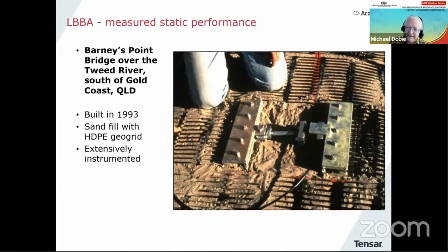And also because, again, it was early use of this technology in Australia, it was quite carefully instrumented. So, for example, one thing that we used were these load bolts to try and measure the load in the geogrid. Now, there was one slight issue with that approach because the load bolt system is so stiff, it was attracting too much load. So, in fact, they overread the load in the geogrid. So, measuring load in geogrid is not easy.